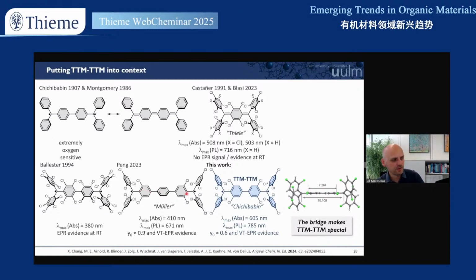It's longer, so you would expect a redshift. But what happens is that these phenylenes to the central phenylene are tilting out of planarity. We see what is normal for oligophenylenes, that there's a dihedral angle that is tilted on average in solution and even in the solid state. So that explains why the Müller diradical here reported in 2023 has much blue shifted optical properties compared to our compound.